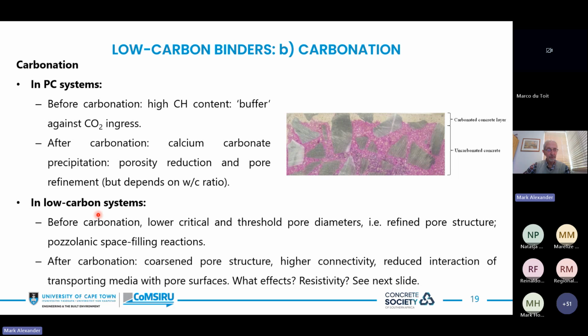So that's an important fact. However, in low carbon systems, before carbonation, these are pretty good materials. Lower critical and threshold pore diameters, there's a refined pore structure, and so on. But after carbonation, the jury is still out on the question of coarsened pore structure, higher connectivity, reduced interaction of transport media with pore surfaces. What are these effects? Well, let's have a look.